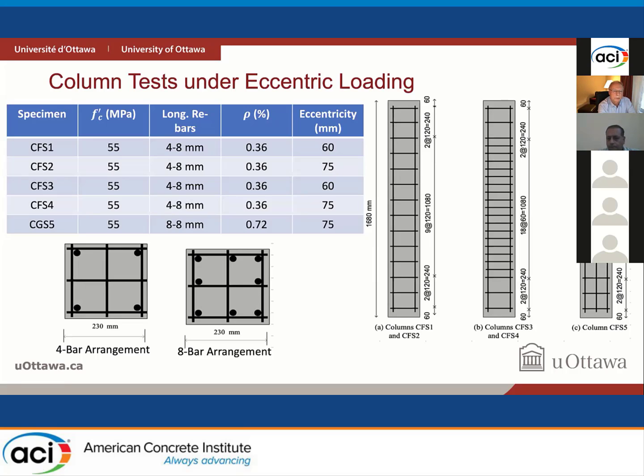reinforced with CFRP bars. And also, more importantly, develop column interaction diagrams for FRP reinforced columns, where, of course, the concept of yielding of reinforcement does not exist. And I will show you the correlation between interaction diagrams and the test results as well. The concrete strength on the day of testing was 55 MPa, and percentage of reinforcement was 0.36 when we used 4-bar arrangements, and it was twice the amount when we used 8-bar arrangement with eccentricities either 60 or 75 millimeters.